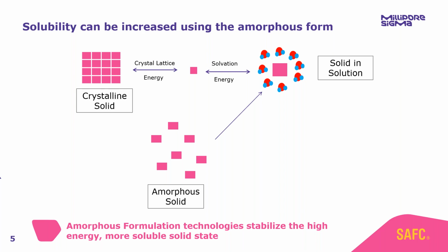The one caveat is that the amorphous solid is not a thermodynamic equilibrium for most molecules. The amorphous solid has an excess amount of free energy, and the system does not like this. It wants to get rid of that excess energy, and it does this by forming crystal lattices. So our amorphous solid would typically recrystallize. So in order to take advantage of the potentially enhanced solubility that the amorphous solid form can provide us, we need to stabilize this high energy, more soluble solid state.